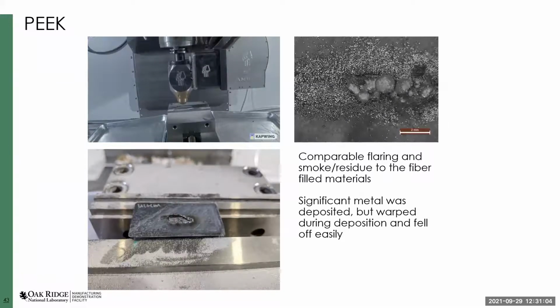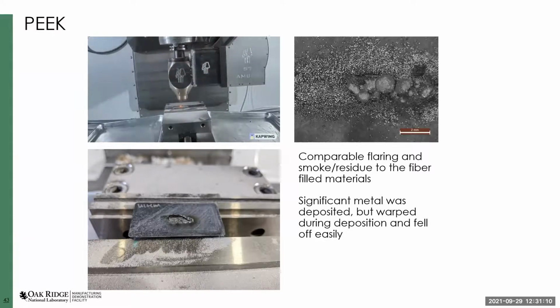And then I also tried it with a high temperature material called PEEK, which I expected to perform better, but was actually pretty surprised that it had a lot of flaring, which is generally a little bit less safe. And the material tended to expand. So basically the exposure to the laser and to the molten material resulted in such a transformation of the polymer that it actually expanded and shifted the metal deposition. So this was actually the least promising of the polymers as a support structure, which was definitely a very interesting result.